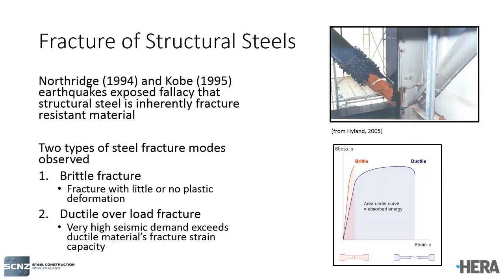Firstly, there was brittle fracture. If we want to understand brittle fracture, if we were to do a tensile test, pull out a test sample and put it in a tensile test machine, and plot stress versus strain, we can contrast brittle and ductile behaviour. If we had brittle type behaviour, once the steel reached its elastic limit, we would get very little plastic deformation before the material fractured, so that's brittle fracture. In contrast, if we had ductile behaviour, once the steel reached its elastic limit, we would get a transition from elastic to plastic behaviour. We would get a significant amount of plastic deformation before the material eventually failed.